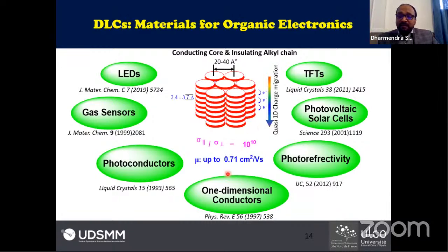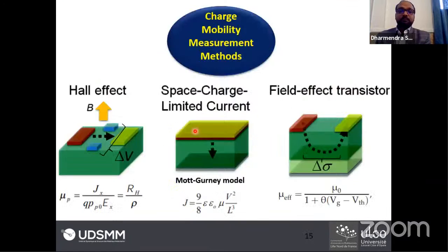So why are these interesting? Because the charge mobility is very, very high for organic compounds, up to 0.71 centimeter square per volt per second. And the electrical anisotropy along the column and perpendicular to the column is very, very high. It's approximately 10 to the power 10. So these discotic materials are very good for TFTs, photovoltaic solar cells, one-dimensional conductors, LEDs, and so on.